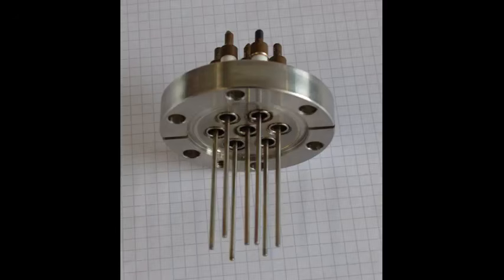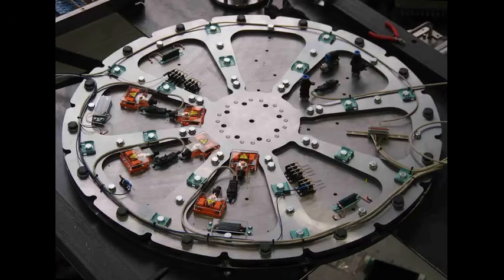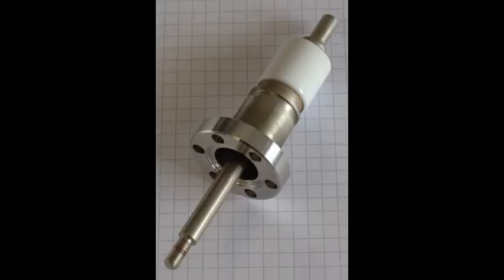One side can be at atmospheric pressure, while the other is under ultra-high vacuum. The part may be heated, cooled to cryogenic temperature, exposed to radiation, or surrounded by aggressive plasma. Yet the basic demand is familiar: hold the conductor precisely, stop electricity from taking the wrong path, survive temperature change, and maintain a seal. New alumina grades now insulate equipment operating from several thousand volts to nearly 1,000,000 volts. They appear in mass spectrometers, electron microscopes, medical CT and MRI systems, X-ray equipment, and accelerator hardware. The shape may be a flat substrate, a tube, a ring, a chamber, or a multi-pin connector. But the material logic is the same logic that made the spark plug insulator possible.